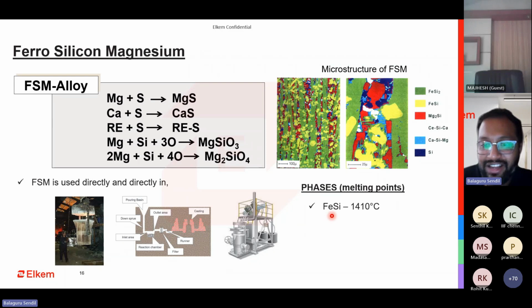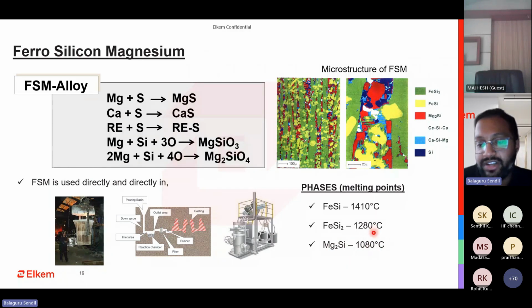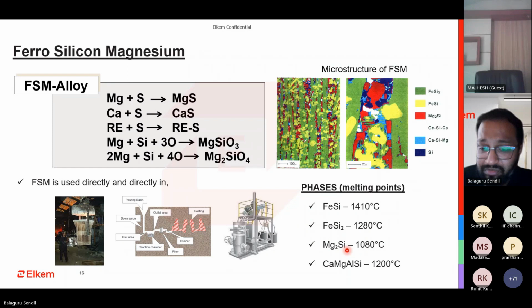If you look at it, the ferrosilicon as such is a carrying element. It has a very high melting point. How this is impactful is that when you are doing the ductile iron treatment, this will make sure that the reaction starts very late. So more metal is going into your treatment ladle. And the ferrosilicon FeSi2 has a slightly lower melting point. And then we have the magnesium silicide Mg2Si, which starts at about 1080. So you can see here that pure magnesium is about 600, this is about 1100. So this is the impact of having silicon and iron in your FSM. And then we have calcium magnesium silicide. This has a very high melting point.